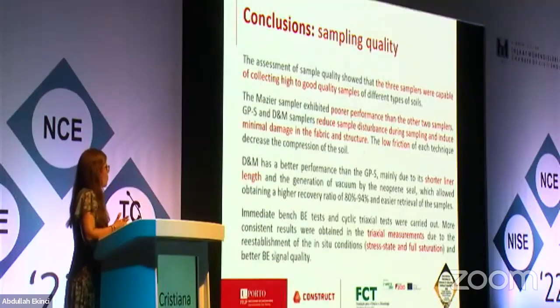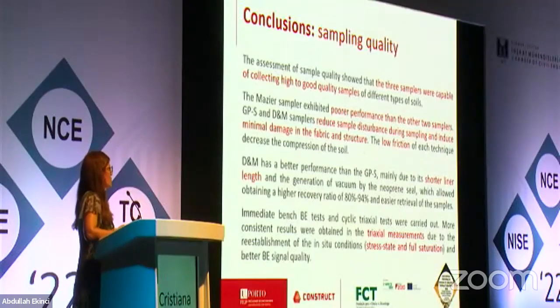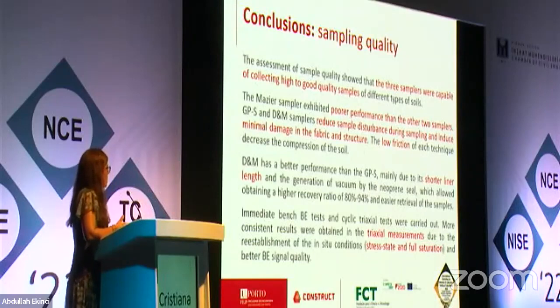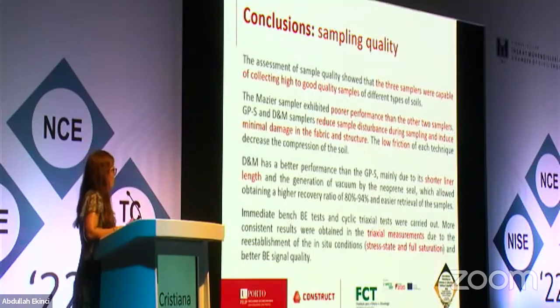The ones here didn't perform so well, and I didn't go into details on the sampling quality because it wasn't the main topic, but the most advanced samplers proved to be the best, and they were able to reduce significantly the sample disturbance during sampling and induce minimal damage in the fabric. Obviously, the other stages of transport and preparation are also very important to get these high quality specimens for testing.